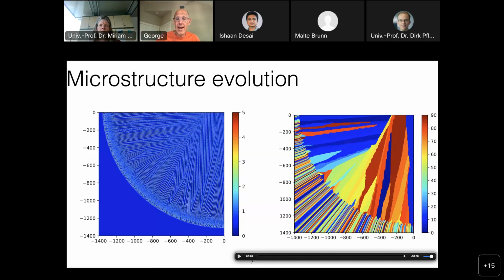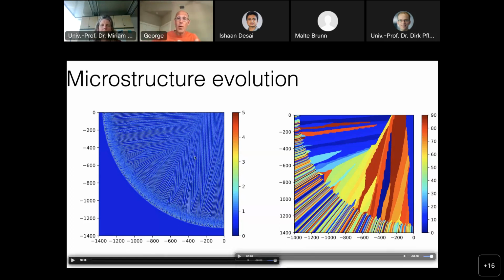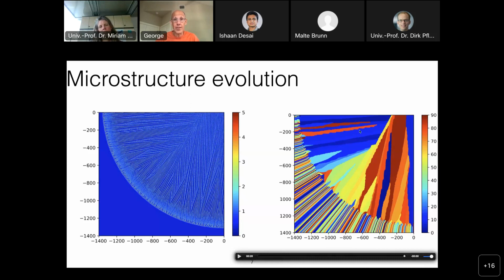substrate already has grains, and here we just take a uniform distribution with the size and the orientation, and that distribution, in combination with the heat transfer, affects what the final grain structure will be. So in essence, when we do the solidification, since this is unknown, the quantities of interest are random variables that depend on this random distribution of initial grains. And that implies that whenever we do a simulation, even for a single melt pool, we have to perform this simulation several times in order to sample this distribution and obtain statistics for the microstructure, the texture here. Does this make sense? Any questions so far? What the problem statement is?